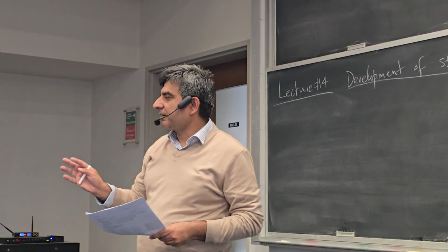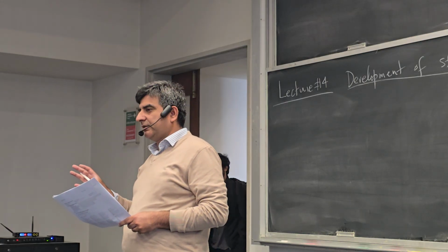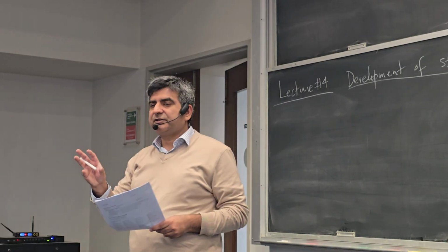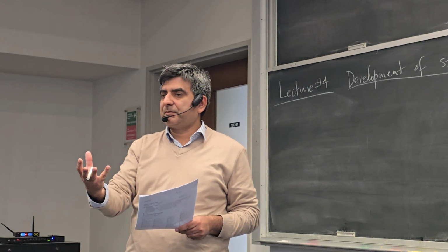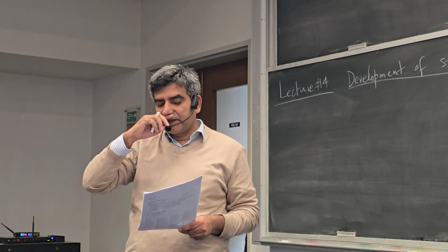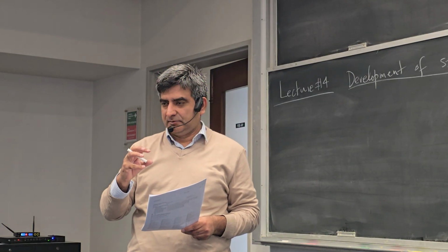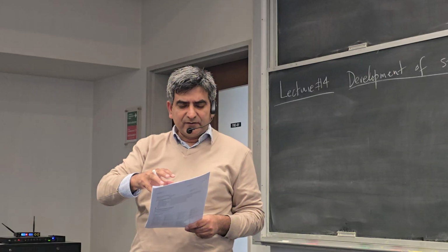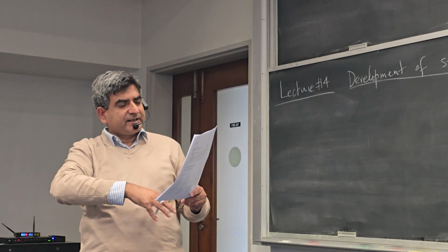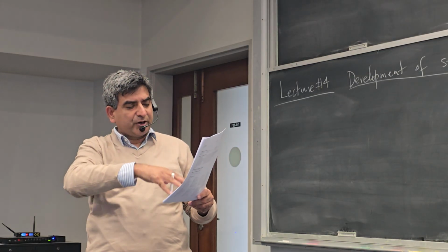Crystal systems are demarcated according to the shape of the unit cell. So the symmetry operations in the point group necessitate that the unit cell has a particular shape. And that's why you can club together the different kinds of point groups into a crystal system. Correct? So you have crystal systems, the 7 crystal systems, and a collection of point groups.